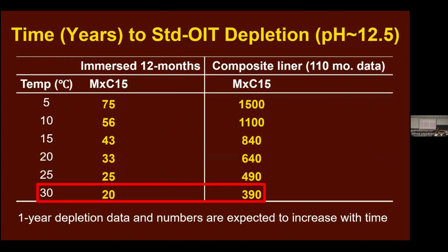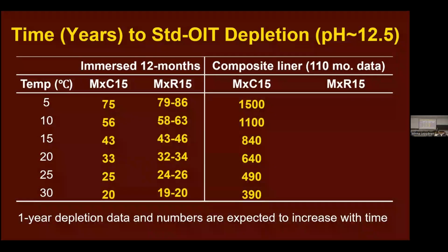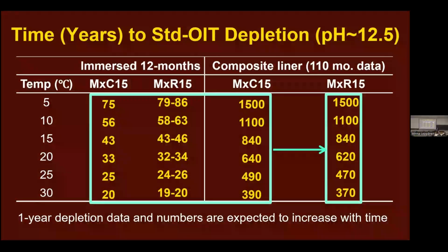So let's look at some numbers. If I test for 12 months, I project 20 years at 30 degrees C. If I test for about 9 years, that increases to 390. The longer I test, the longer the time becomes, because in early times it's dominated by the things that deplete quickly. This is a different product. You can see it's very much the same, and so we can extrapolate it the same.